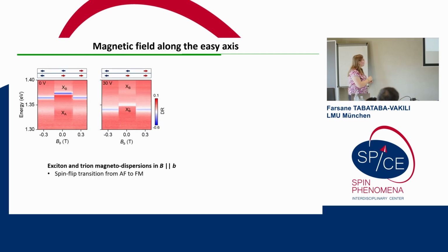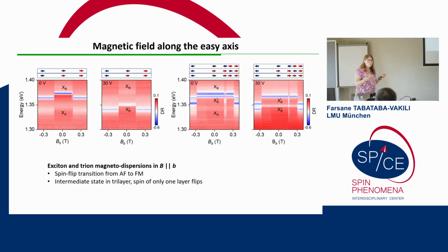Now, let's apply a magnetic field along the in-plane B axis. So here, we observe this abrupt jump in exciton energy at a critical magnetic field where the spin flips. We see this again for XA, XB, and XB minus. And then, in the trilayer, we observe another curious intermediate state here, where only the energy of the lower exciton here jumps. So here we believe that we have a state where the spin of only one layer flips, such that we have two adjacent layers with ferromagnetic order and two adjacent layers with antiferromagnetic order.